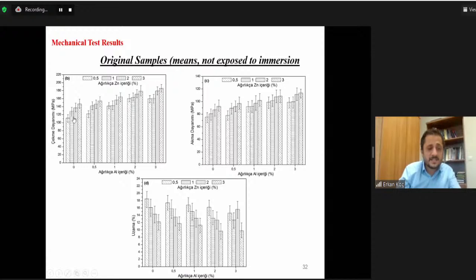The tensile strength increases linearly again as the amount of zinc increases for each alloy. The yield strength of the alloys is quite parallel to their tensile strength, and elongation, unlike the yield and tensile strength, decreases linearly as the aluminium and zinc amounts increase. This is caused by the increase of intermetallics. You know, in the microstructure, the increase in crack formation points, okay?